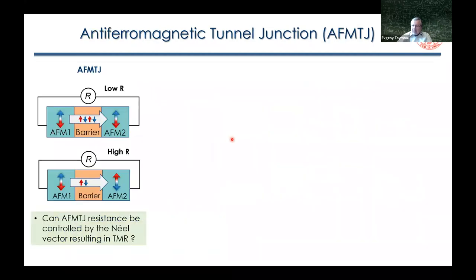And this is the idea of an antiferromagnetic tunnel junction. So it would be desirable for antiferromagnetic spintronics to have such a device where we have two antiferromagnets separated by some barrier layer in such a way that depending on the relative orientation of the Néel vector, we can have low or high resistance. So very similar idea to what we have in a magnetic tunnel junction. Now, the question is whether it's possible to realize or not.